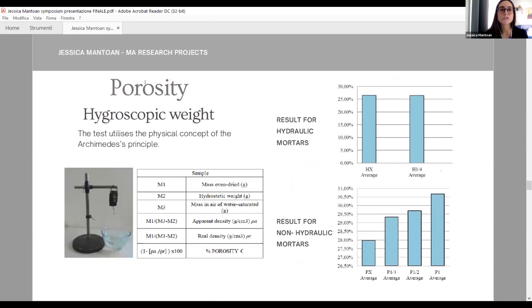In that respect, I decided to do further research about the porosity of the mortar through the study of the hydrostatic weight. That is a physical concept based on the Archimedes principle. It's a really easy way to estimate the percentage of porosity of a material, in which you have to carry out just three measures. The first one is the measure of the sample dry. The second one is the measure of the sample immersed in water, also called hydrostatic weight. And the third measure is the measure of your sample out of the water, but completely saturated with water. Once you have the three measures, you can start to calculate the apparent and real density. And after that, you are able to estimate the percentage of porosity of your material.